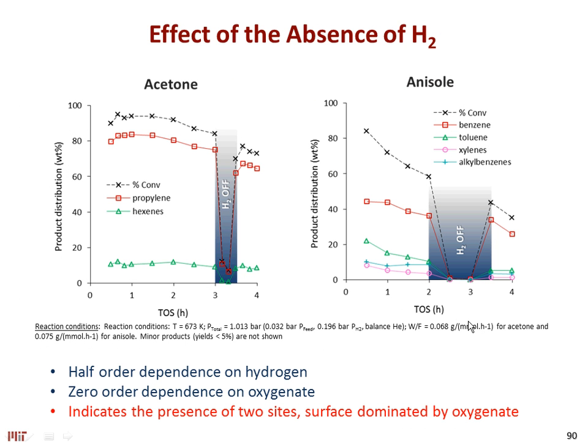But we also know that hydrogen is quite important. For instance, if you turn hydrogen off, the reactivity immediately decreases. You turn it back on, and it's as if you had never turned it off, except that it deactivates a little bit quicker. We see from our order studies a half-order dependence on hydrogen. This suggests that we have dissociative adsorption on one site, but we also see zero-order dependence at all different types of conditions on the oxygenate.